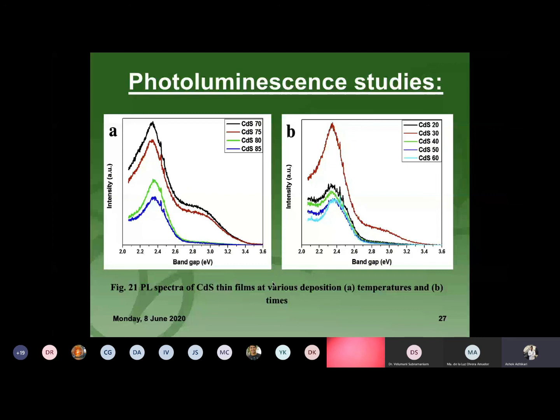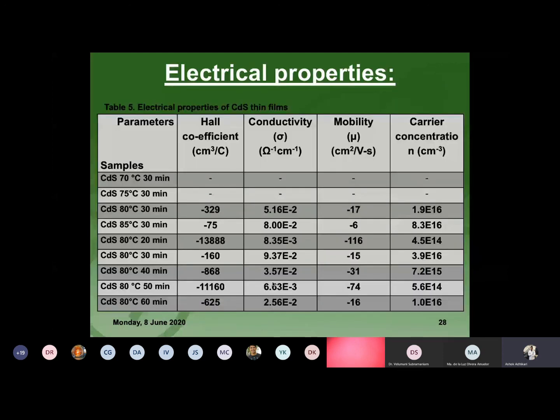Finally, we checked the electrical properties from table 5. The negative value of Hall coefficients signifies the n-type nature of the material. We also calculated conductivity, mobility, and carrier concentration of the film. The conductivity of the film is on the order of 10 to the minus 2 to minus 3, and the carrier concentration observed is 10 to the 14 to 10 to the 16 per centimeter cubed.